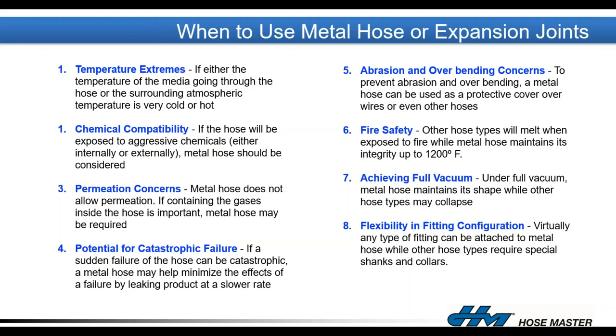Another thing is the potential for catastrophic failure. Even if a metal corrugated hose is grossly overpressurized, way above its working pressure and beyond its rated burst pressure, it generally doesn't suffer a catastrophic failure. With metal hoses, what happens if it's overpressurized? The corrugations start to inflate and eventually the metal fatigues and a small crack forms, allowing the product to leak at a slower rate. Metal hoses don't explode like hand grenades and send shrapnel flying around.